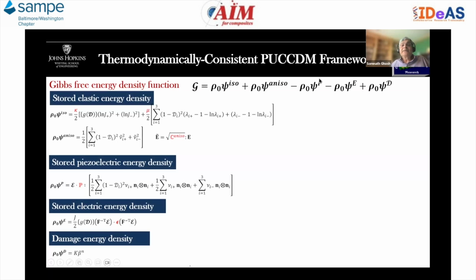Now, the thermodynamically consistent PUCCDM framework consists of the Gibbs free energy representation. The only thing is, now we are representing a homogenized upscale representation. So rather than individually resolving each of the cracks, we represent the aggregated effect in the form of a damage mechanics law. So we have the stored elastic energy representing the aggregate of the microstructural elastic deformation. Then we have the stored piezoelectric energy density. Again, this is an aggregate, and it is reducing because of the increase of the damage as the microstructural cracks evolve. Then we have the stored electric energy density and the damage energy density.